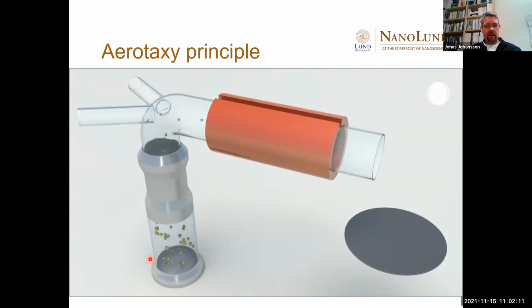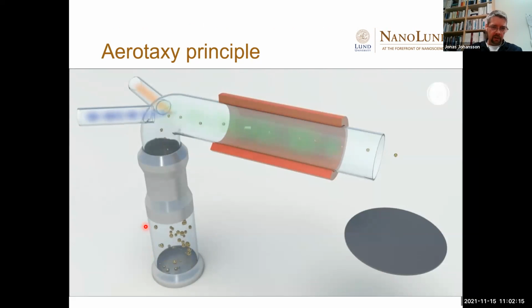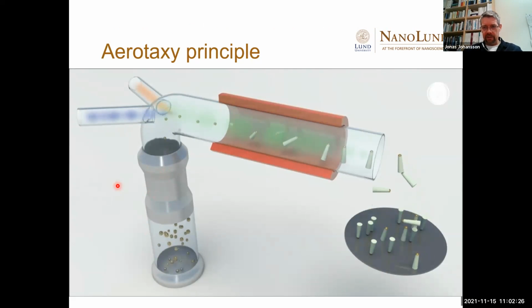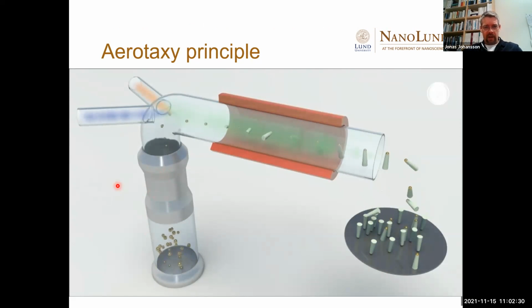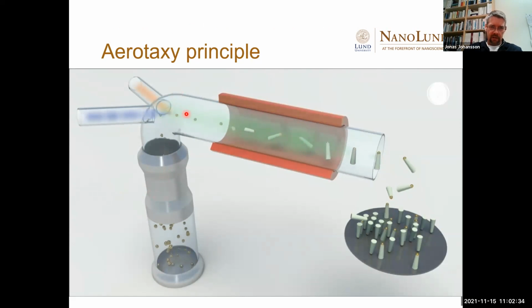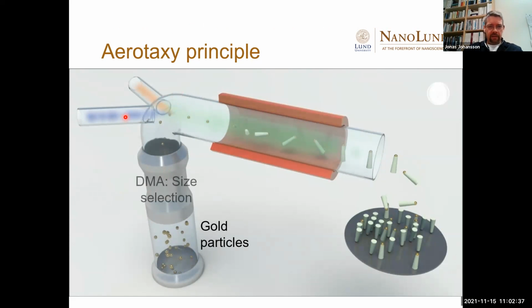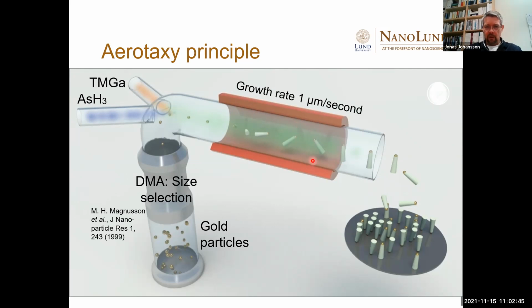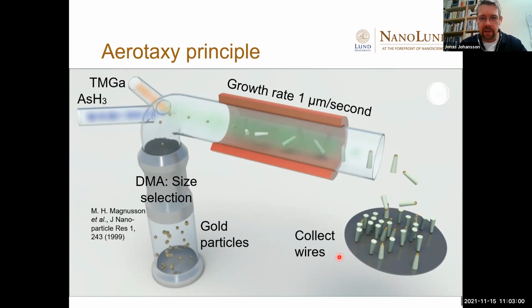It works like this, that we insert our gold particles, which we make in the aerosol phase, and we size select them here in this device, which is known as a differential mobility analyzer. So we have more or less single size gold particles, and then precursor flows which are mixed, and then we heat this up in a furnace and collect the nanowires afterwards. So we can collect them like this. We can use an electric field to make them aligned like this. So the growth rate here is actually quite high. It's 1 micrometer per second.